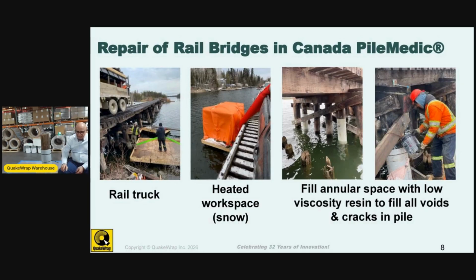In this case, as you see, they are wrapping the laminates tightly around the pile without any annular space. Usually the unevenness of the surface of the timber pile itself creates a small cavity to allow the introduction of this low viscosity resin, and then it finds its way through the cracks.